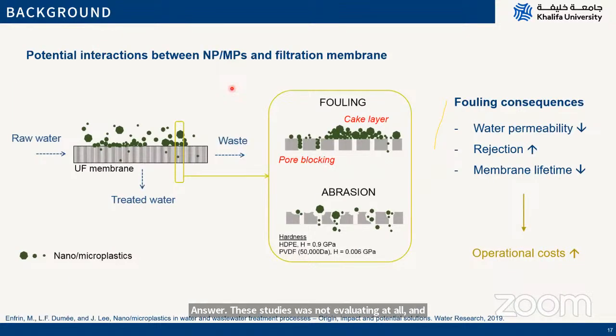And what issue can they bring? Well, one of the major things is that when microplastics accumulate or cluster, they can generate fouling layers, and they can again absorb proteins, biological matter, or whatnot, and generate a cake layer on the surface of the membrane, leading to pore blocking and decrease of performance. At the same time, we have seen some physical abrasion of these materials with a high shear stress caused by the flow rate of water containing these microplastics on the surface of the membranes, leading to defects and premature loss of performance.